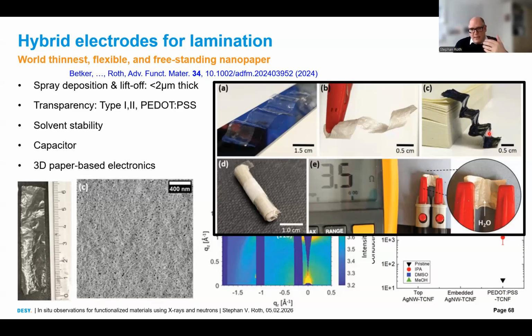Of course, as I said, it depends. If you want a cluster layer with, say, gold or silver clusters, I didn't show this, then you can have a nominal thickness, if you calculate the effective thickness, of 1 or 2 nanometers. So you have very well dispersed metal clusters on a surface. It depends on the functionality. If you want an electrode, we think here that 100 to 200 nanometers is sufficient if you have it on a substrate.